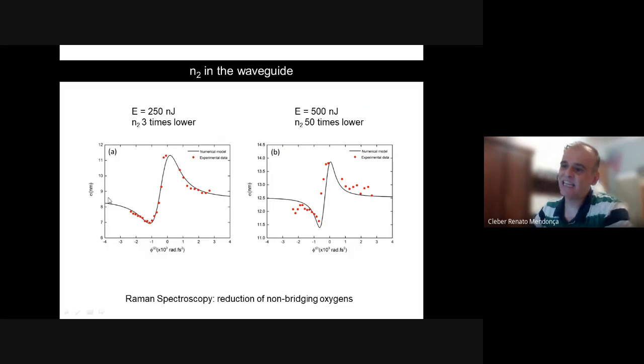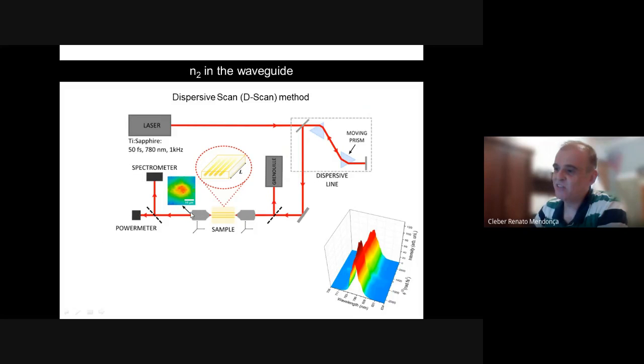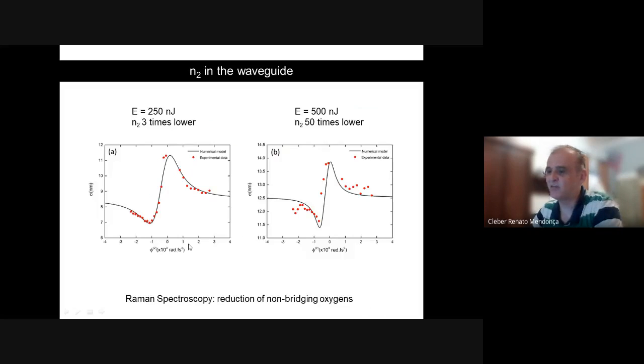And then what we can get is something like this, which is actually how broad is the pulse. So how many new frequencies I'm generating in the output of the waveguide as a function of the dispersion here in the dispersive line. So that's what I'm showing here. Here is the dispersion, and here is the broadening of my femtosecond pulse. Okay, so what can we get from here? Of course, this broadening is related to the nonlinearity N2.